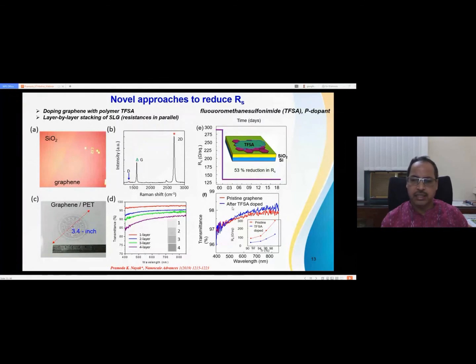Whereas when you see the transmittance and sheet resistance plotted, for the doped graphene in comparison to the pristine, there is no such change. But when you talk about the sheet resistance, you can see the pristine graphene going from 300 ohm per square to 90 ohm per square. But in the TFSA doped graphene, we get 134 ohm per square. When you go to 4-layer, it goes to around 40 ohm per square.